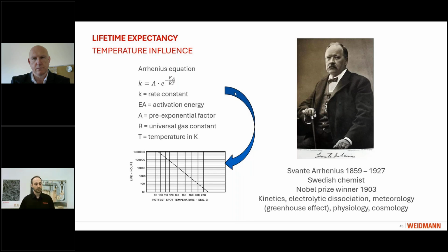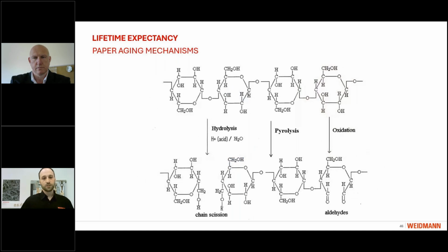So the question we have to ask ourselves is, which processes take place for the degree of polymerization to be reduced? And there are three distinct processes. The first one is hydrolysis. Hydrolysis uses the water or the acid part of the water to make the chain be disrupted. Now, very critical here to know is that this hydrolysis is an autocatalytic reaction, meaning the educts that it uses for the reaction generate the product, which again displays the educt for the next reaction. So the amount of water that you have in the beginning is kind of a head start for the degradation. And the less water, the smaller your head start. So this is really why we need to have the material as dry as possible before we get in, because this reaction really benefits from any water that was still in.